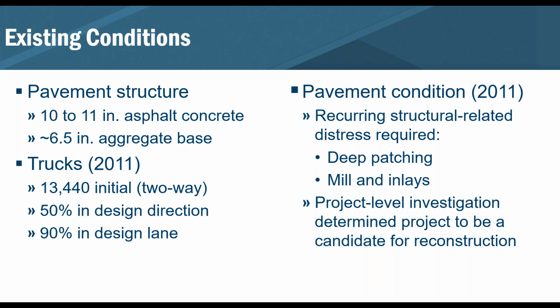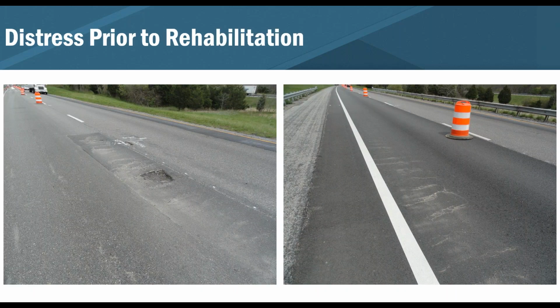And that's just some looks at what the distress was, typical distress prior to the rehabilitation. So this is back in 2011. You can see there's a patch on the left that has a series of potholes in it. You can see quite a bit of fatigue cracking in the patch as well. The image on the right, I was going, hey, wait a minute, that's like a mill and inlay. Now it's actually a patch of a patch type of thing. And you can see again the fatigue cracking is coming up pretty nicely in the right wheel path and actually showing some staining. So we're getting some of the fine material coming up through the subgrade. So you're pretty guaranteed that those fatigue cracks run through the entire depth of the asphalt layer.